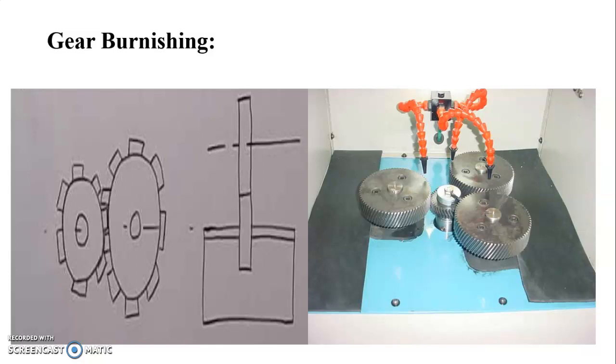Gear burnishing is a cold finishing process for gear teeth, used for gears after cutting but before hardening to improve surface finish and uniformity. The gear is mounted on a vertical reciprocating shaft and meshed with three hardened and ground burnishing gears. These gears are power driven and fed into the cut gear and rotated through a few turns in both directions. This makes the gear surface smooth and also imparts a little hardness to it. The load is provided by pneumatic, hydraulic or electric means.